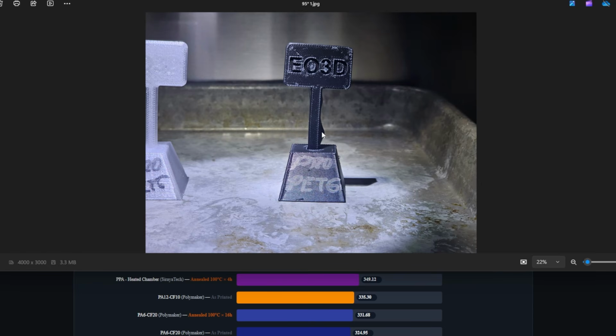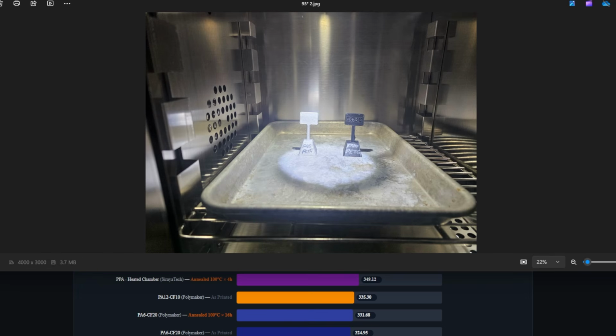And there we go at 95 degrees. You can see it's starting to bow a little bit. It's got another one of those little spots starting to show up here. It's almost like the material's growing and blowing out back there. PCTG, you can see here against the edge of the camera screen, it's still pretty square. And here they are zoomed out. This is 95 degrees Celsius.